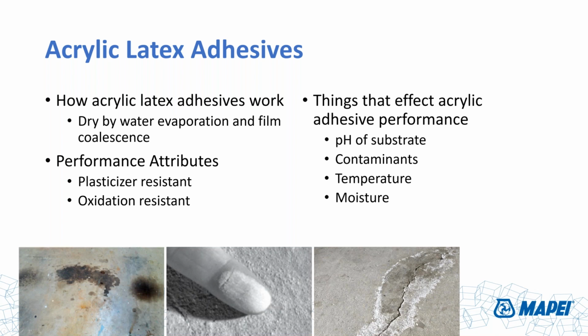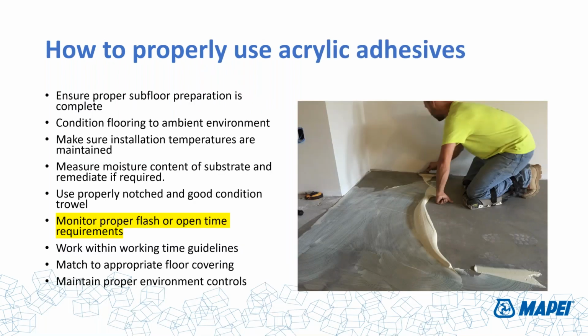The pH of a substrate is very important to watch for. These products are good, again, up to a range of 11. If it gets higher than that, 12 to 14, I've seen acrylics hydrolyze. You pull off the flooring, and you'll smell a ketone, like a fingernail polish smell, off of them. That's very indicative of the fact that the high pH has caused that acrylic to fall apart. The contaminants, the temperature, and the moisture, again, are all things you have to be aware of for acrylics.